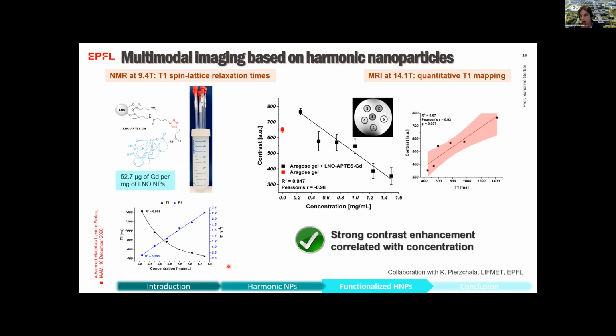Then we move to MRI for quantitative T1 mapping. Here you can see this is the image of the phantom, showing a strong contrast enhancement that is correlated directly with the concentration of the nanoparticles in the sample. So this combined system really opens the way for multimodal imaging using these harmonic nanoparticles.